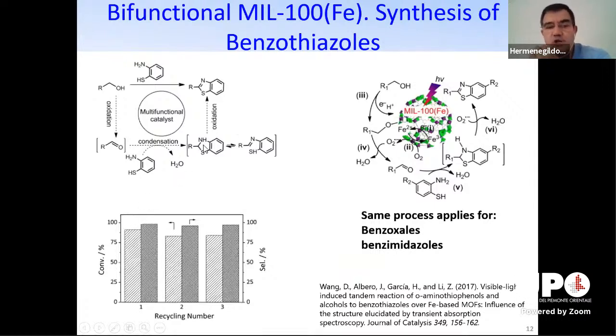This is another tandem reaction in which we have an oxidation functionality. This oxidation is going to be run photochemically, because one of the activities of MOFs is that they can absorb light. They can absorb light by the ligand. Some of the MOFs have color. If they have color, it means that they are able to absorb visible light. And with visible light activation, you can promote the oxidation to the aldehyde, and then the aldehyde condenses, similar to what we have commented previously in the case of benzaldehyde, except that in this case we have nitrogen and sulfur, and what we end up with is a benzothiazole. Similarly, this mechanism also works with benzoxazoles, in which this is an oxygen, and also a benzimidazole.